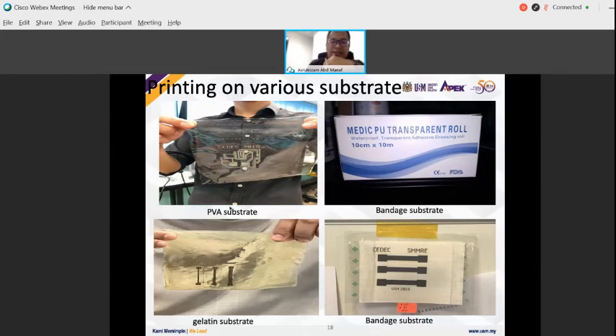And then we also just did a test on another substrate, gelatin. That may be an application for humidity sensors. And this is an example using a bandage, the Medic PU transparent, and we also tried it. We also printed using inkjet printing on the bandage.